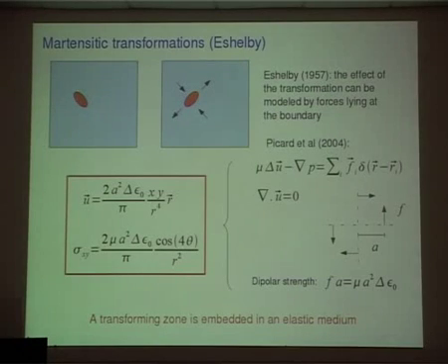Okay, so the problem now is that when you have a rearrangement, this rearrangement will introduce stresses, and it is then possible that it will trigger another rearrangement. If this occurs, it means that the assumption that these rearrangements are independent events is no longer valid. And the first question we'll ask is whether these rearrangements can be thought of as independent processes or not.